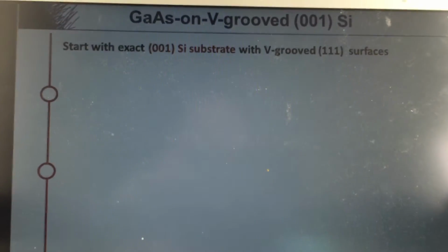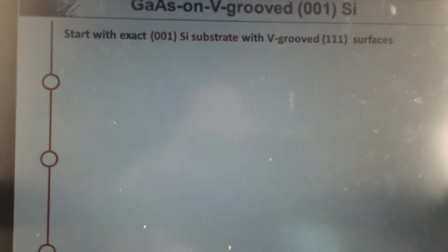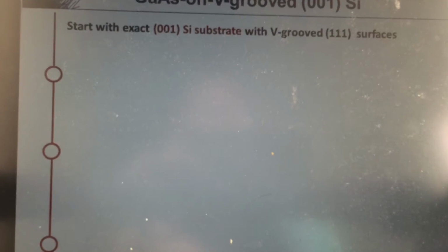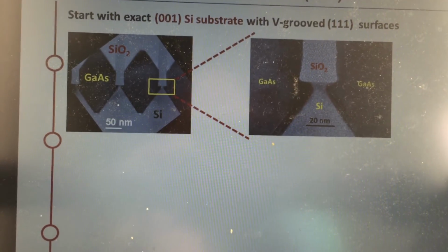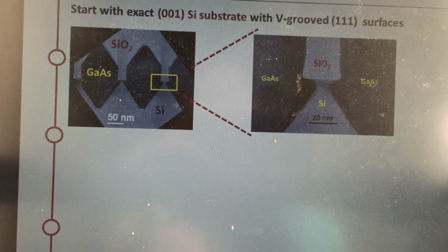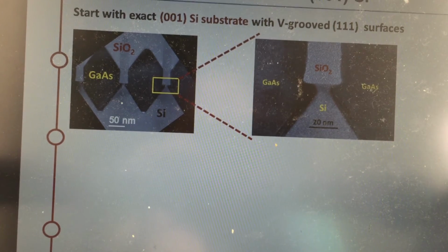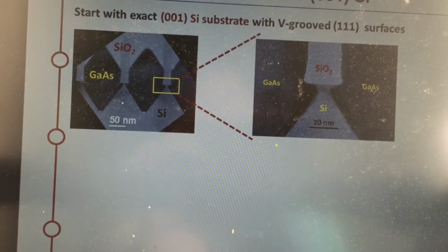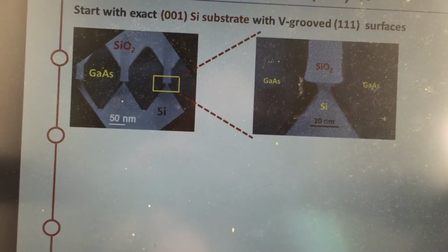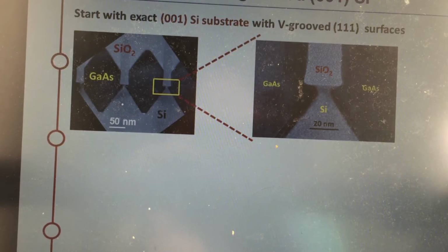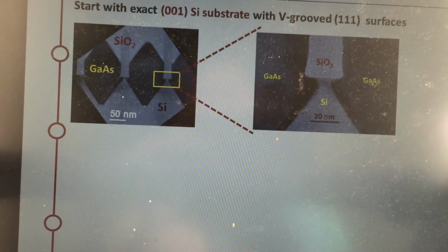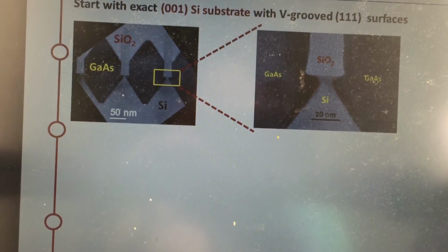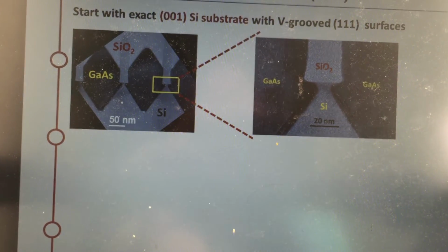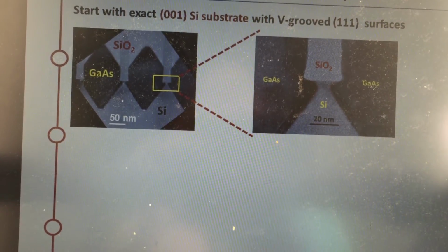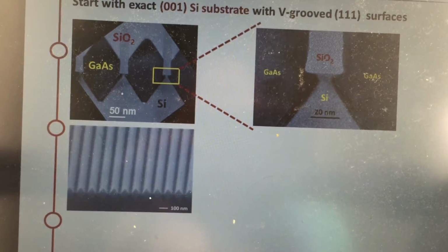So, in our group, we have developed a special way to grow gallium arsenide on wafer group 001 silicon. We start with a nano-patterned silicon substrate and grow the gallium arsenide nanowires inside the trenches, separated by the silicon oxides. Through the aspect ratio trapping process, most defects can be localized in the trenches, and the (111) surface has eliminated any formation of any-phase domains.